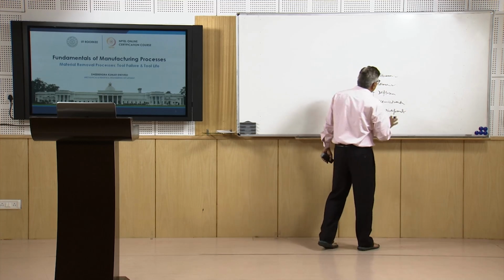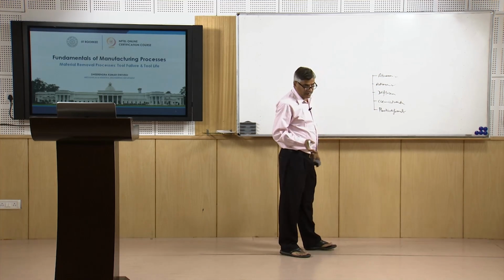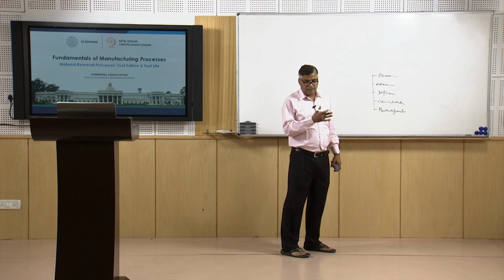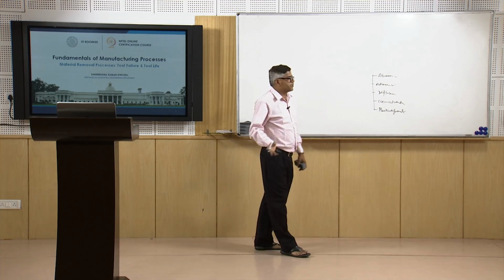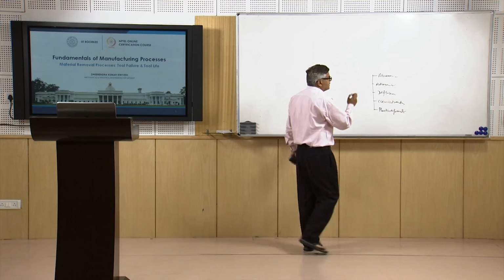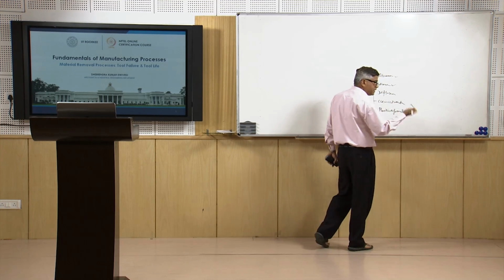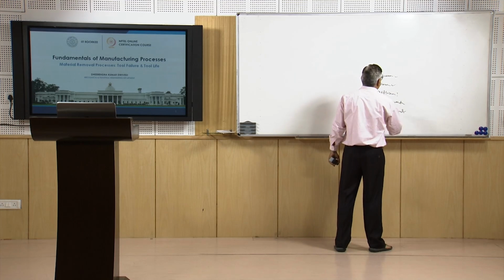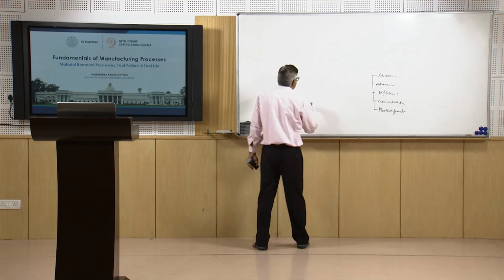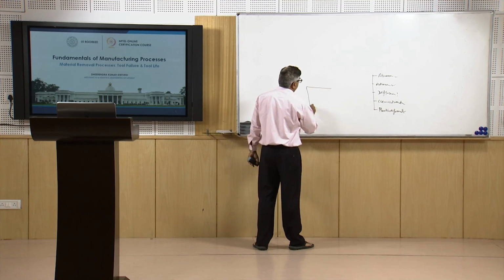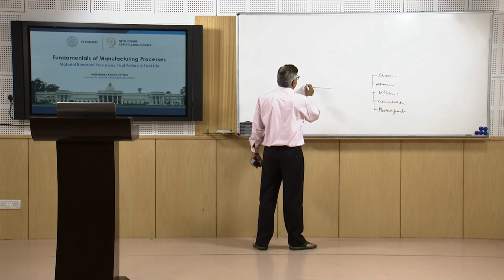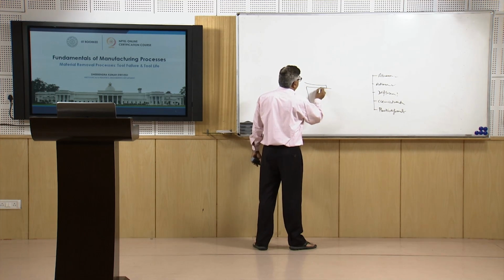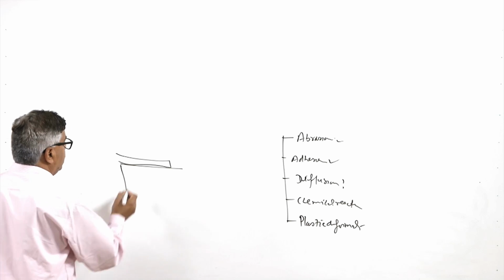There is also Archard's law, which says that the wear volume is inversely proportional to the hardness of the material. Since the rise in temperature reduces the hardness, this in turn increases the wear of the material. Diffusion is another mechanism, wherein a high temperature is generated at the tool chip interface and the chips are in contact with the face of the tool.